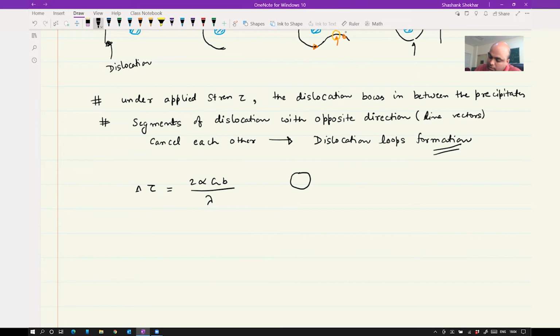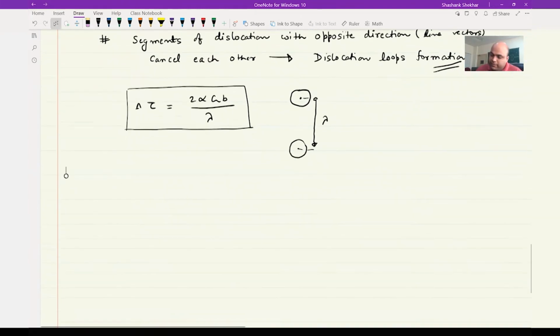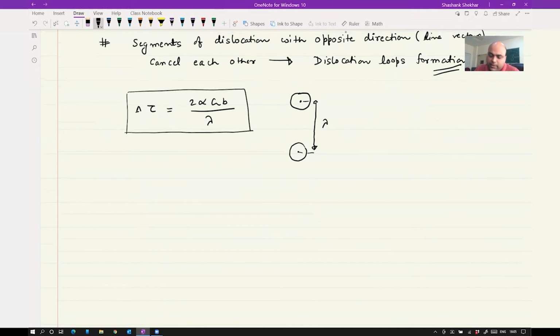So if you have one and second precipitate here, so this distance, okay. So if this is lambda, the increment in the stress for bowing the dislocation will be given as 2 alpha G b by lambda, where lambda is the interparticle distance or spacing. Okay. So overall here, if I want to write similar to what I wrote in the cutting of the precipitate,